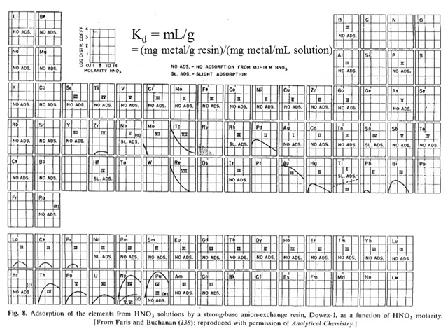This distribution coefficient is in milliliters per gram, so that's really the milligrams or some concentration of metal ion per gram resin, divided by the milligrams or concentration of metal ion per milliliter solution. So your metal ion concentration could be moles, could be milligrams, could be activity. It doesn't matter because it cancels out. But basically what one sees is the larger the distribution coefficient, the greater the metal ion is retained on the resin material.